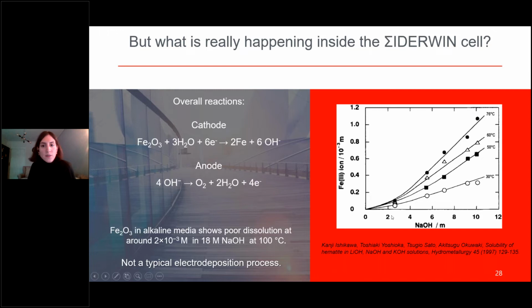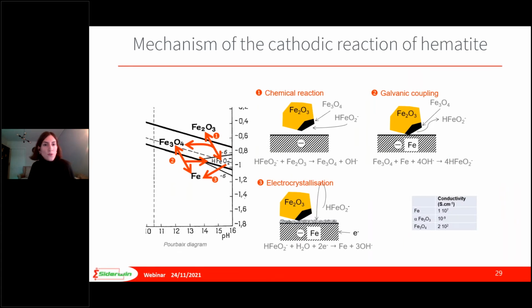That means that the metallic iron is not produced only from the reduction of divalent iron. This means that this type of electrolysis is not a typical electrodeposition process and follows a different route. The mechanism of the cathodic reduction of hematite seems to follow a solid-state reduction mechanism.